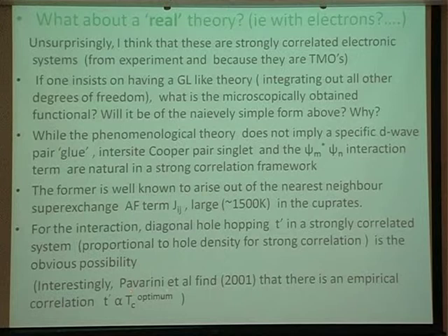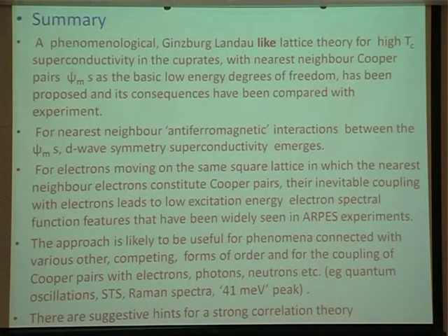Interestingly, long back, two people in the audience and many others did an electronic structure calculation, and found that the diagonal hopping amplitude, which has a much larger energy scale than Tc, was proportional to Tc optimum across several members of this cuprate family. So this seems to suggest to me that maybe strong correlations are actually involved in this process.